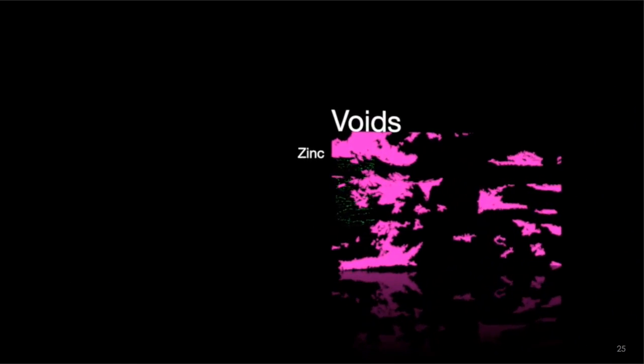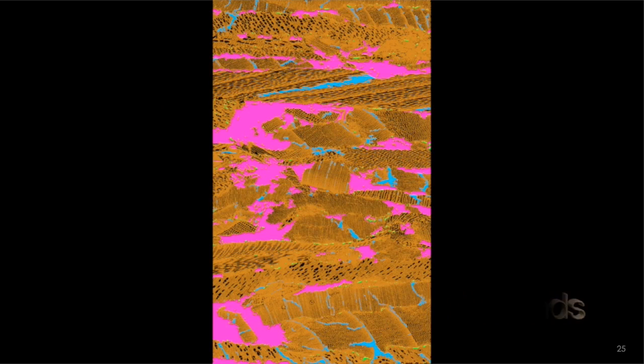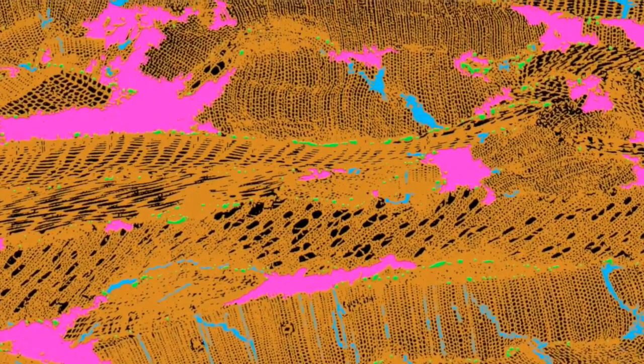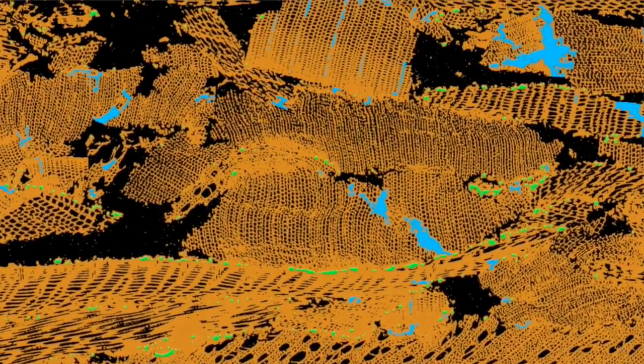This technique is the most time-consuming between all of them, but is the one that gives us the most precise information about the microstructure of the entire sample. So let's go to high magnification to have a look at the cracks and voids that were manually segmented. It takes around 2 weeks to segment one slice, but it's certainly worth it.